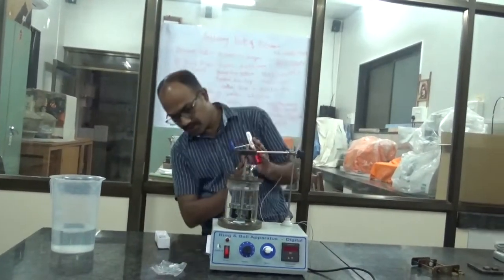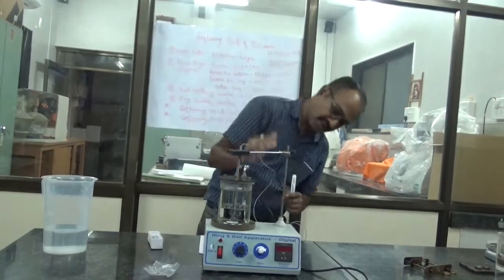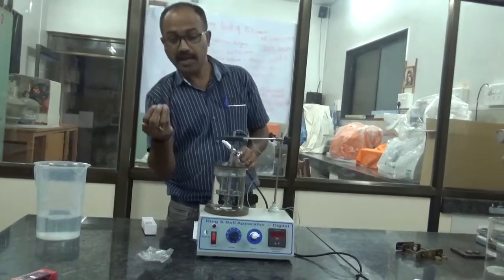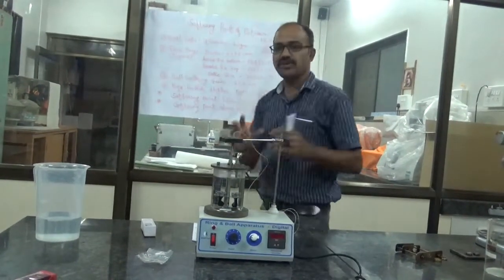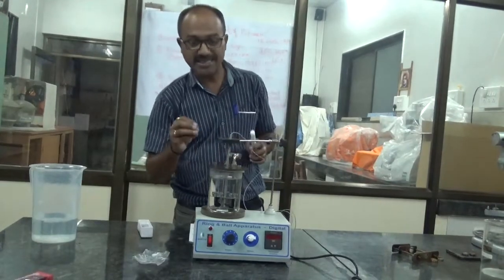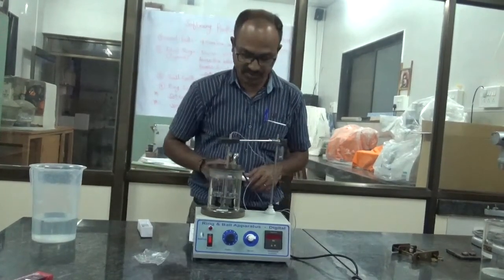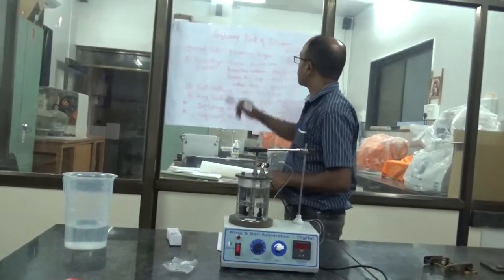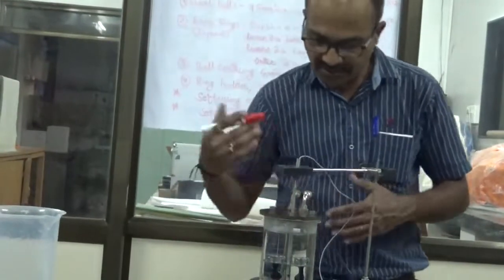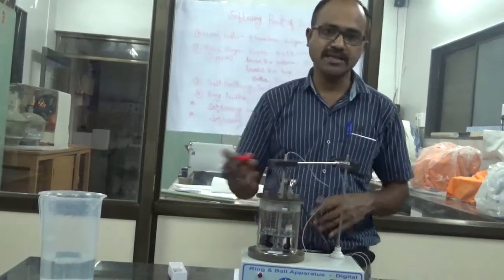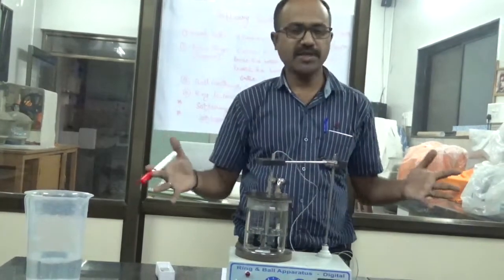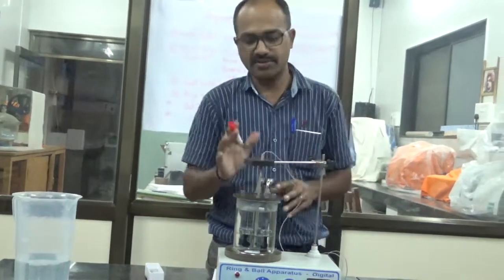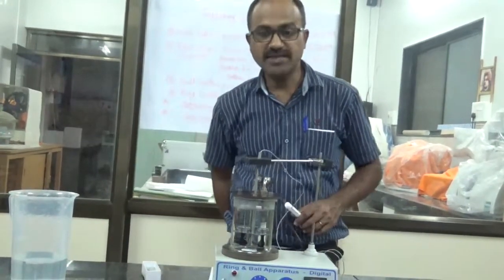The first ball touched the bottom plate at 46 degree and the second ball reached at 46.6. So on average we can say 46.3 degree centigrade is the softening point of the bitumen. With this, our experiment on the softening point is over. You can perform one more test and check the repeatability. If the results are within a permissible limit, you can quote a particular softening point for that bitumen. Thank you students for